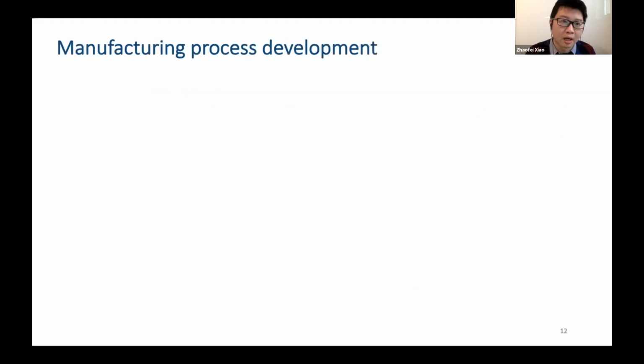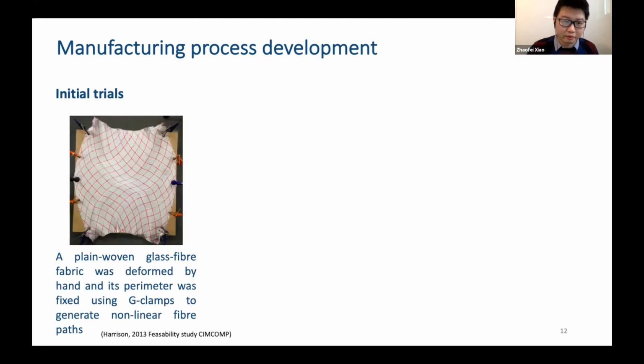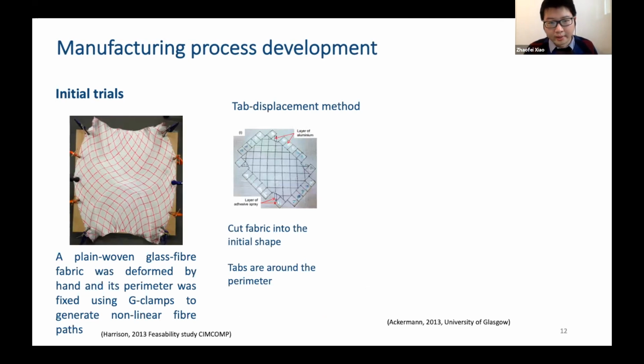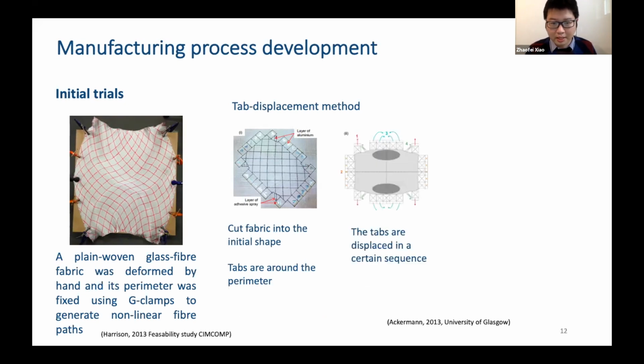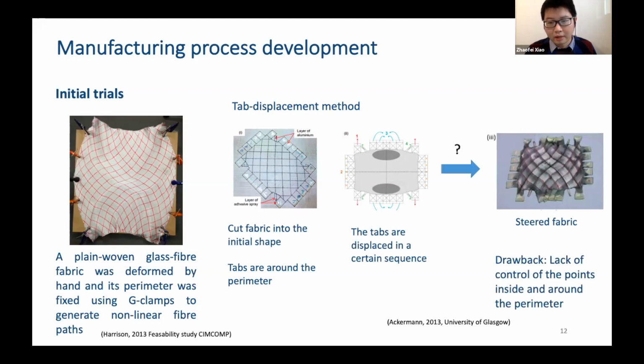Okay, when we're talking about the manufacturing process, as I mentioned before, the story came from the initial manufacturing trial. Then we used a tab-displacement method to manipulate the fabric. So we cut the fabric into its initial shape and also made some tabs around the perimeter. Through displacing those tabs in a certain sequence, we can achieve the steered fabric. However, this method has a main drawback. We lack control of those points inside or around the perimeter. So in order to solve this problem,